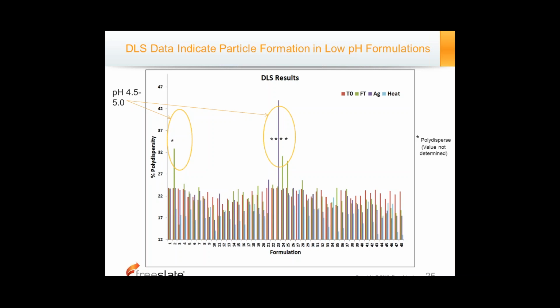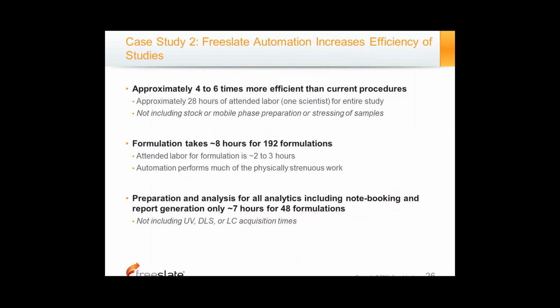And we can see here that the pH formulations at pH 4.5 to 5 had higher percent polydispersity values. In some cases, the system was just not able to even calculate the polydispersity. So this was a good indicator of stability for the different formulations. So overall, what we see from this study is that automation is increasing the efficiency of the study. If we look back at trying to perform these manually, we can see something like a 4 to 6 times more efficient program than what we use currently.